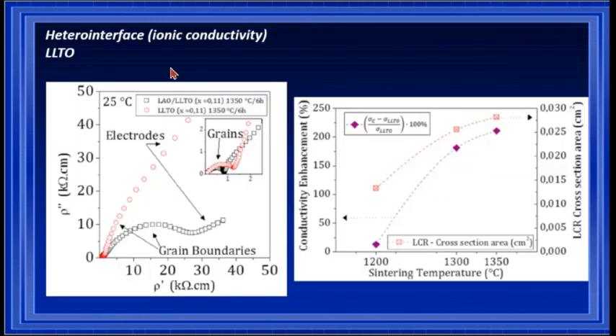When we look at the heterointerface regarding ionic conductivity, we can see that compared to the ceramic without fibers, the crystals, the LCR regions, have much lower resistivity. And when we compare the overall enhancement of the conductivity compared to the ceramic without fibers, we see the same behavior: as the LCR increases, the enhancement also increases, and we got an enhancement of the conductivity up to 200%.